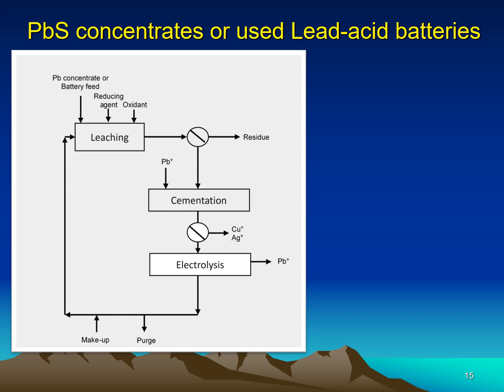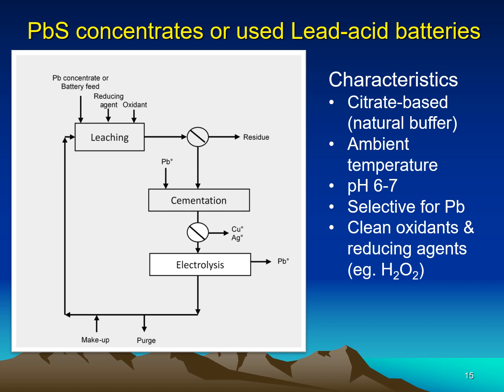and these can be cemented by the addition of lead metal and filtered out as metal, as copper and silver metal. And the pregnant solution is then sent to electrolysis as we had anticipated. After electrolysis, the lean solution contains sulfate ions, which have to be removed before we recycle the solution. So we can take a purge and treat the solution and do a makeup with citrate and water, and recycle that all back to the leaching.